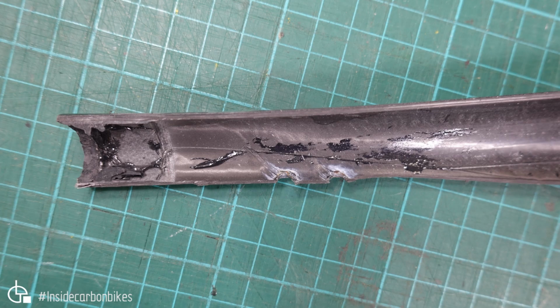And the other side of the chainstay, where we saw some delamination from the drilling, and also the galvanic corrosion, which is that white residue. A little bit of excess adhesive from when they bonded the drop-out in as well, but it's more this galvanic corrosion. I don't understand why there's glass barrier plies in every other area except that area, and that probably sees a lot more moisture because it's so close to the road, and road grime being kicked up, etc.